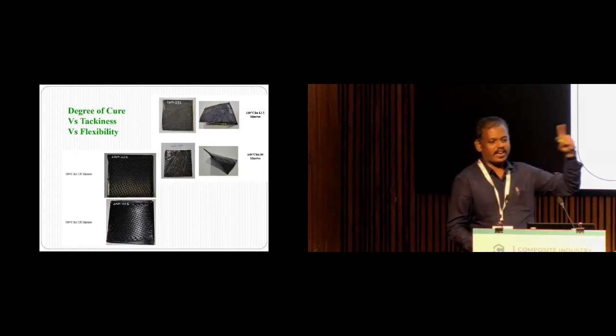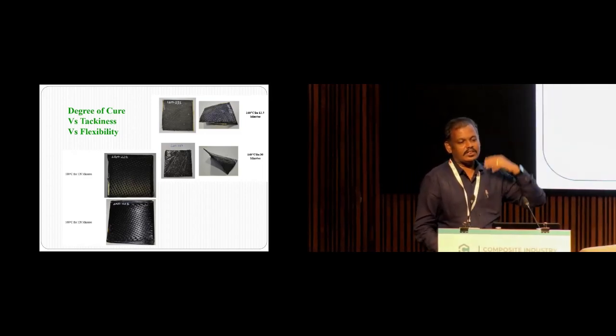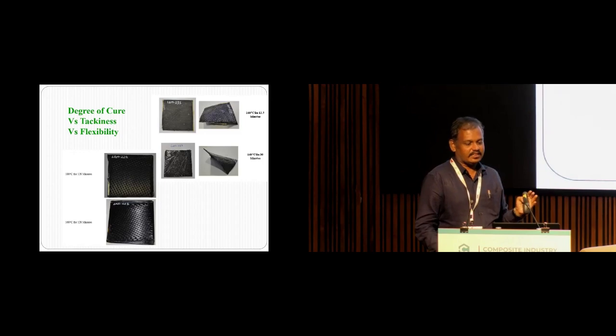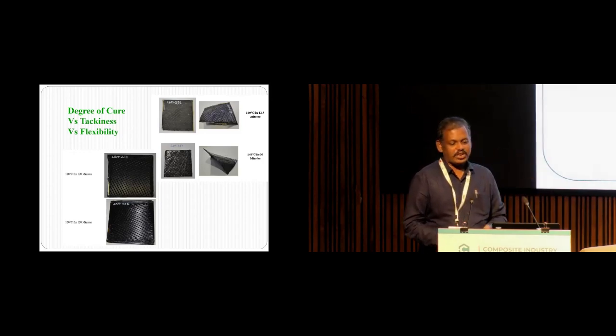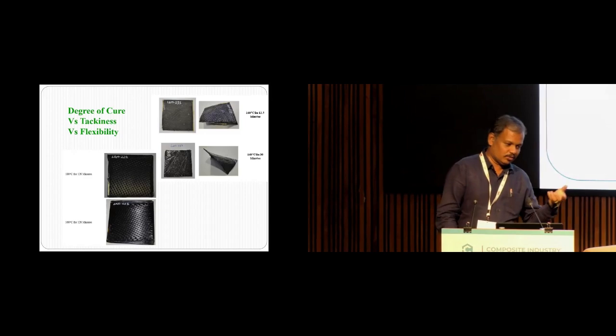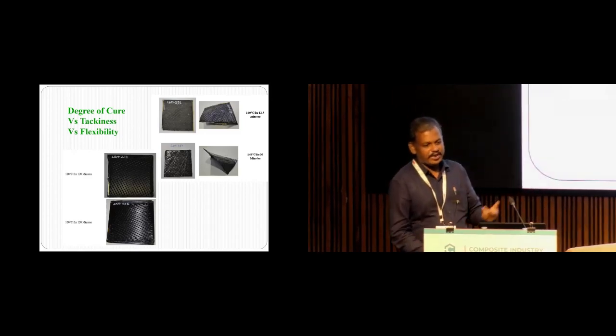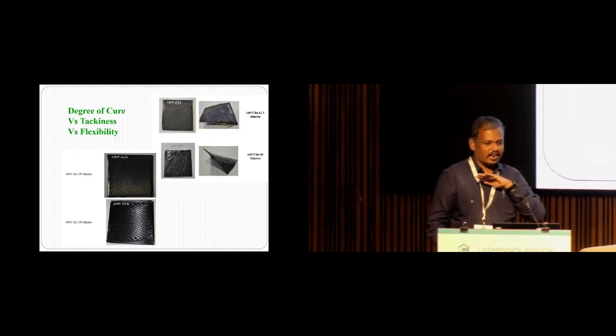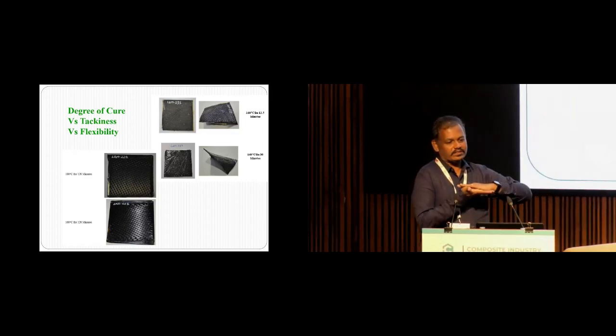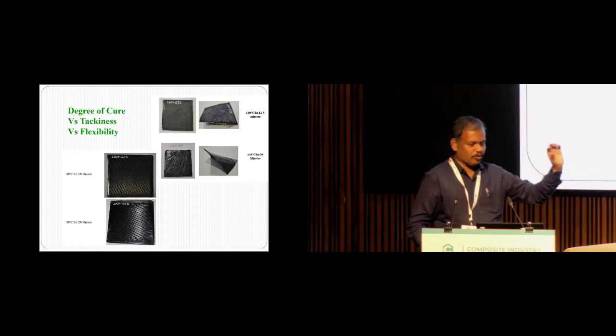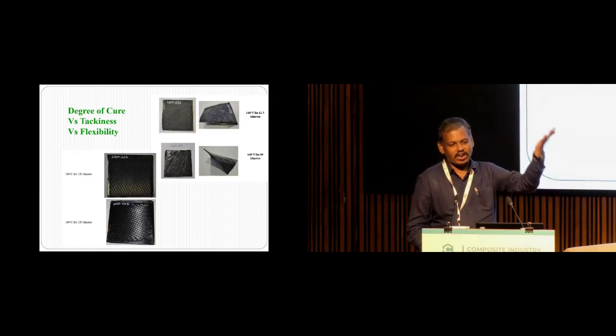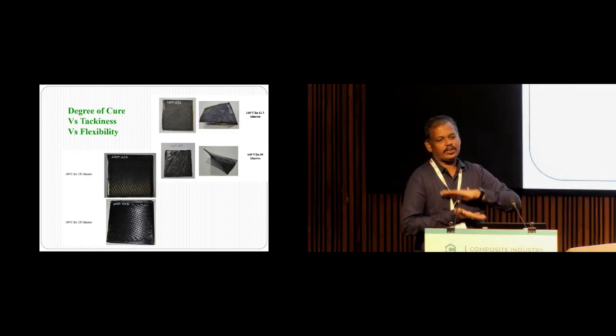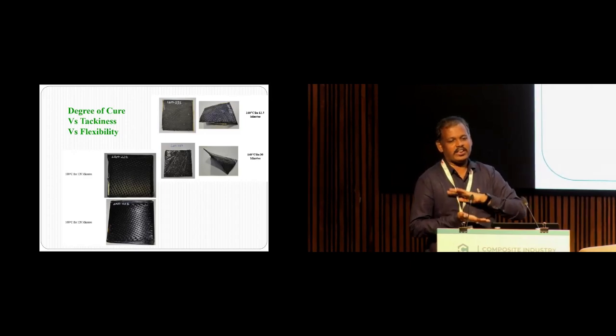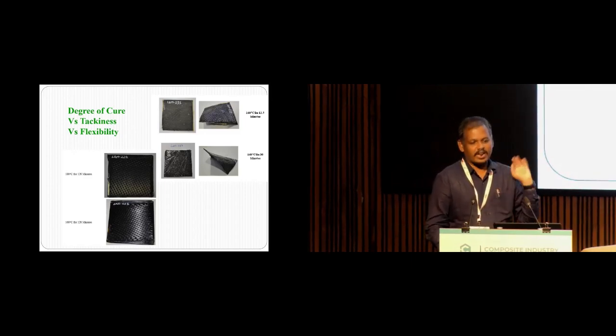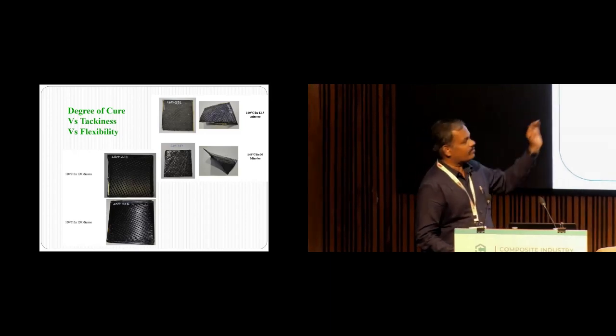But when I go for a higher degree of cure, for example more than 60, 70 percent, it is more disadvantageous, because we said that to produce thick section composite laminate, we will be having thin adhesive film and we will be co-curing. So when this semi-cured composite laminate's degree of cure is higher, there won't be any interfacial curing. Interfacial bonding you may not expect with the thin film adhesive. So you should have a trade-off between degree of cure and the flexibility of the panel.